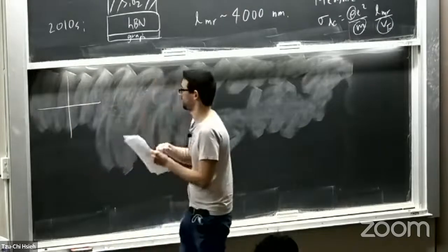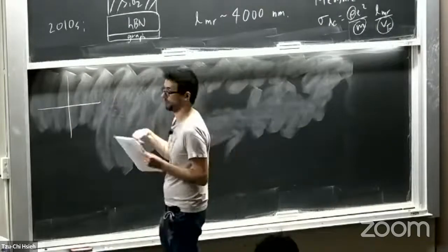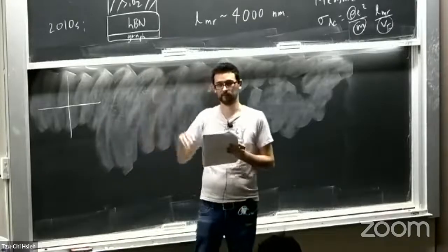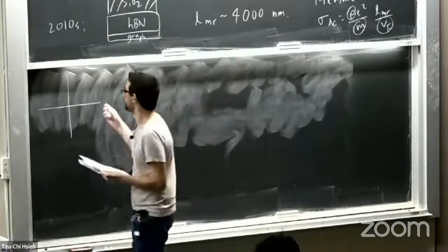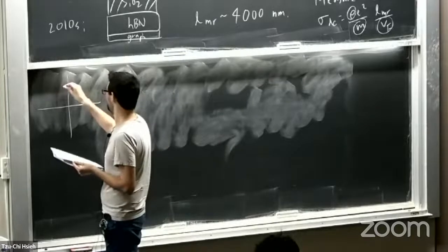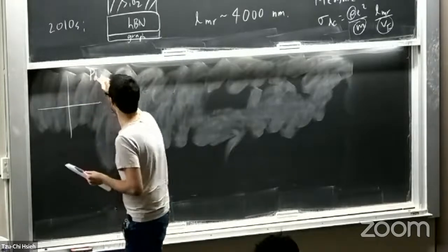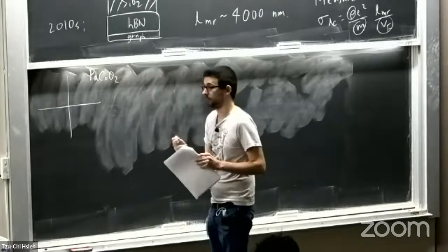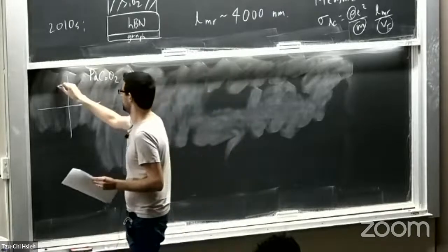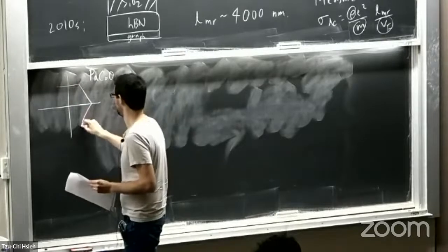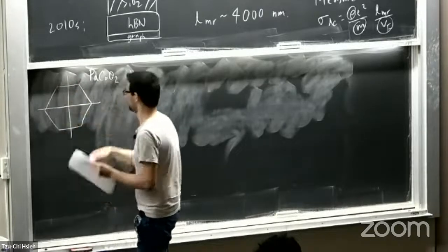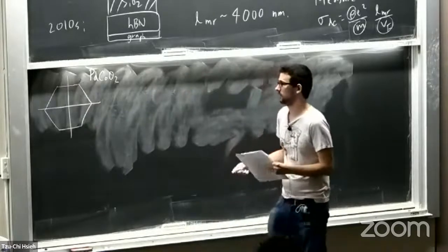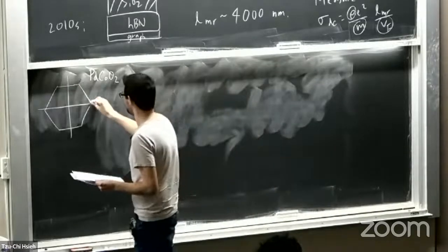If you think about the Fermi surface of the metal, this is just the contour of the kinetic energy at the Fermi energy. So even in a pretty simple metal, like this one I mentioned earlier, palladium cobaltate, which was believed to have hydrodynamic phenomena, if you look at its Fermi surface, it looks more like this. So it's much closer to a polygon than to a circle. Okay. So what do I mean when I sketch this curve?